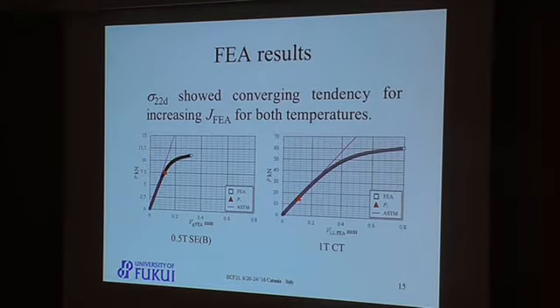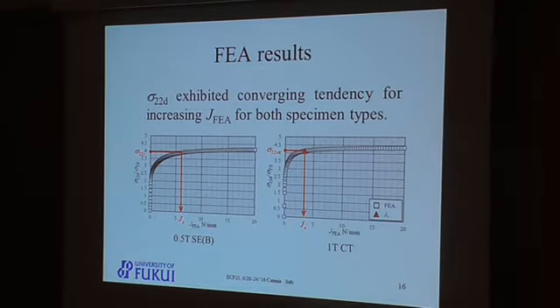After confirming that the linear portion of the load versus displacement diagrams showed good agreement with the relationships described in ASTM E1820, the relationship between σ22d, the crack opening stress σ22 measured at the distance from the crack equal to 4 times CTOD at the specimen midplane, and JFEA was summarized in these figures. For both specimen types, σ22d showed a converging tendency for increasing load, as expected.